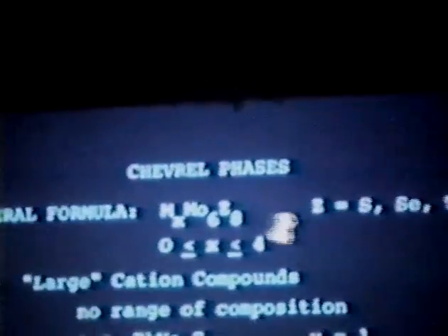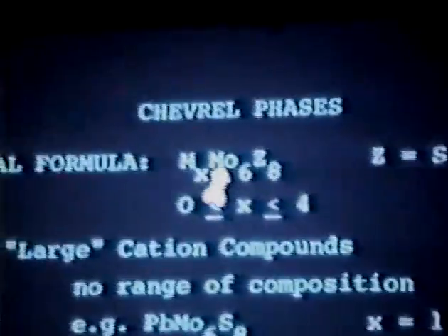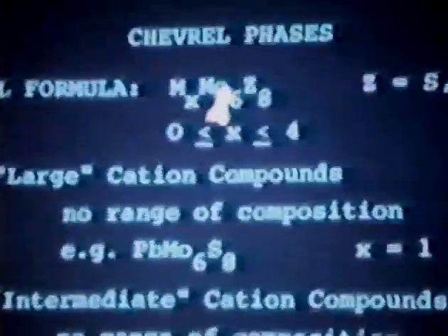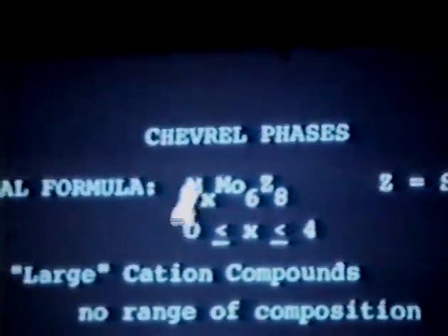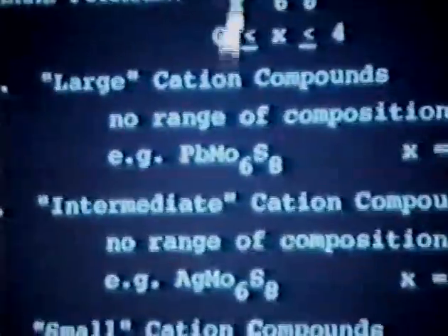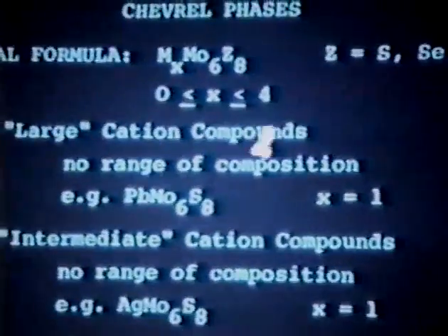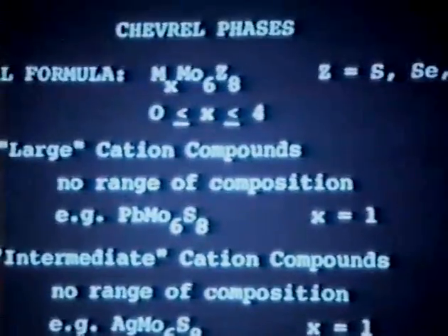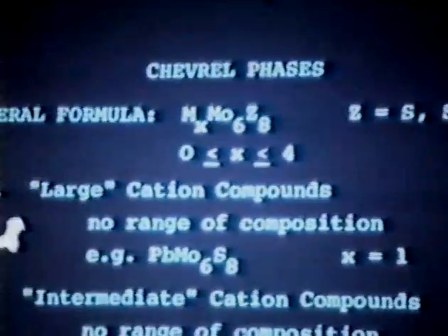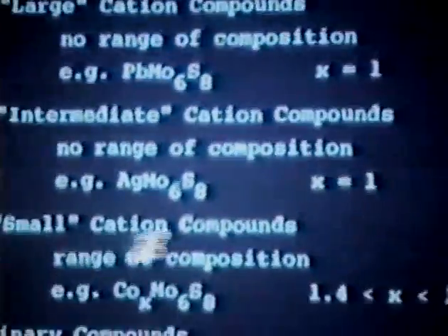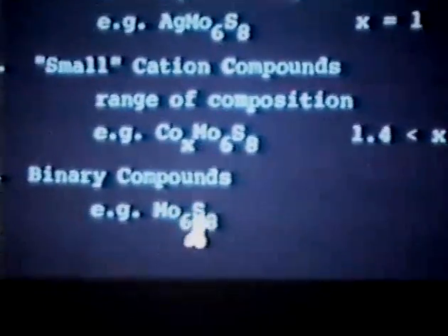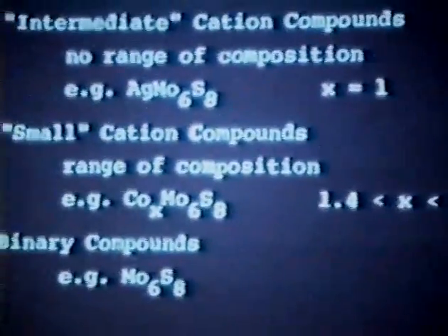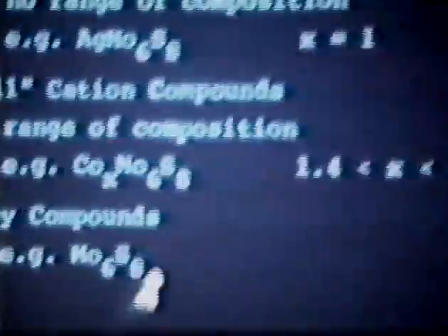There actually are several families of Chevrel phases, but the ones that we're interested in are the chalcogenides, which are based on sulfur. The basic building block of these molybdenum Chevrel phase compounds is Mo6S8. There are ternary metals which one can introduce into these compounds, and there's a very large number of ternary metals with various stoichiometries that are possible. You can classify the Chevrel phase compounds as large cation materials, intermediate cation materials, small cation materials, and then the binary compound Mo6S8, which I'll dismiss right away since we never found this material to be stable under HDS conditions. It always converted to MoS2. In fact, you make this compound by extracting the ternary metal from some of these other ternary metal compounds.